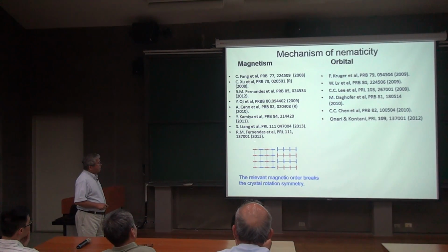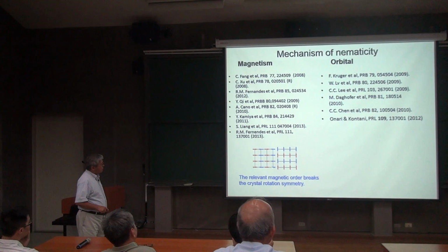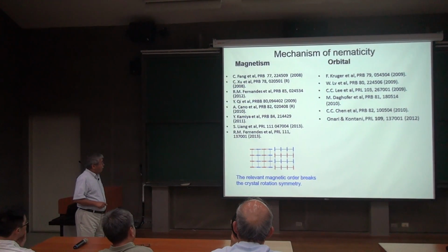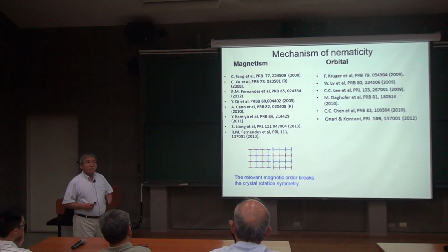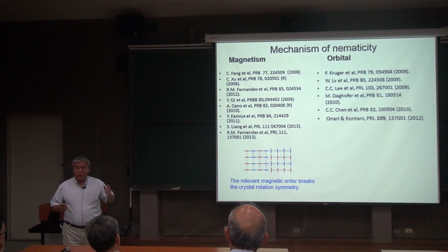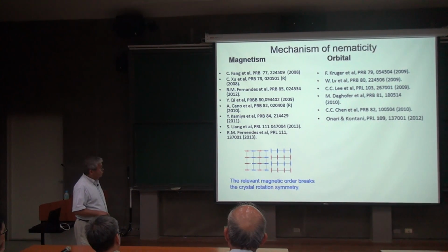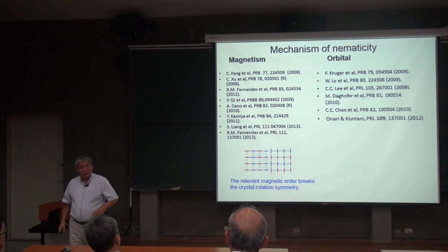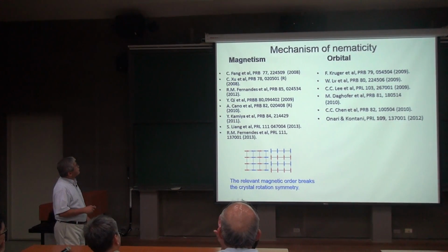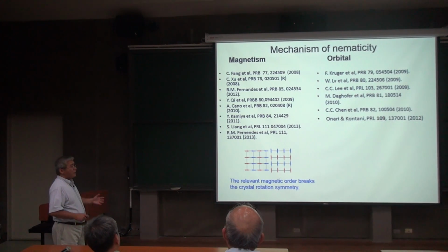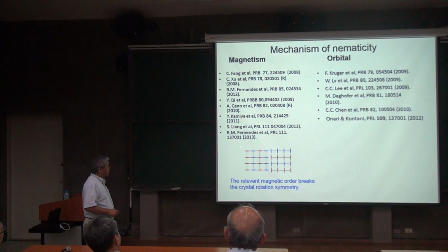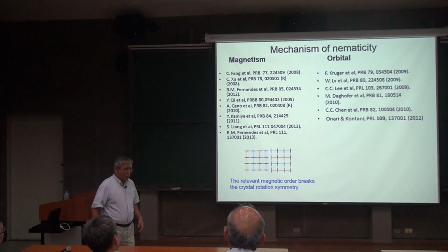You have spins ferromagnetically aligned in the vertical direction and antiferromagnetically aligned in the horizontal direction. Of course, such a magnetic pattern not only spontaneously breaks the spin rotation symmetry, but also breaks the crystal rotation symmetry. Because if you rotate this pattern by 90 degrees, it becomes this pattern, and they are not equivalent to each other. Here, the ferromagnetic alignment is in the horizontal rather than in the vertical direction. So the magnetism school has a very secure foundation, because the rotation symmetry breaking is ultimately connected to the fact that the magnetically ordered state also breaks the rotation symmetry.